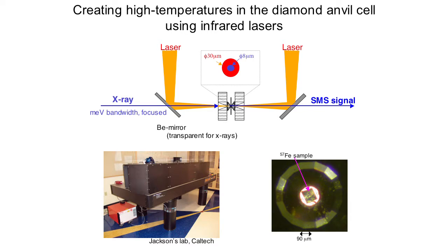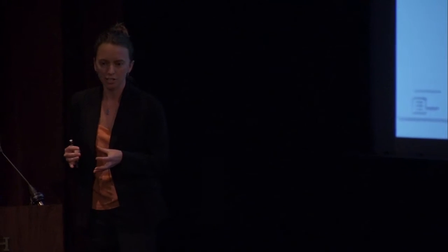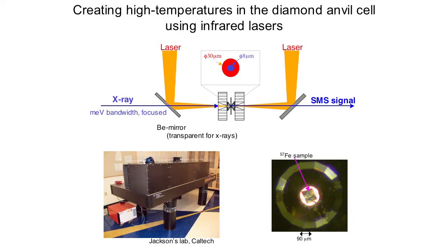The focus will be on the melting point and how we use those vibrational properties to know an accurate melting point of an iron or an iron alloy. We have an infrared laser that is focused in line with the X-rays to the sample that's been squeezed inside the diamond anvil cell. And we have a detector out here that detects the signal. And in our lab, we also have a laser heating system that we're able to at least test the sample configurations and do phase relation studies in the future. So here is the iron metal foil that's inside the sample chamber. It's only about 90 microns in diameter, so that's about 0.09 millimeters. So very tiny.